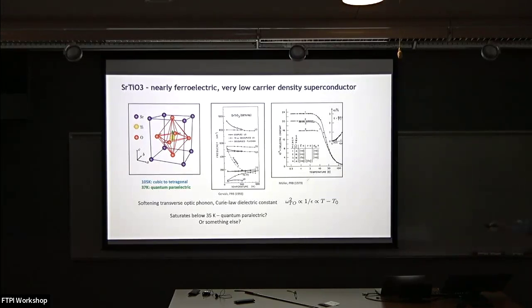You know that because, of course, if it does go off center, it will generate a dipole moment, and the material will become ferroelectric. And the proximity to ferroelectricity involves looking at the dielectric constant, or rather the inverse of the dielectric constant. And so this is rising. This is basically Curie law. And the Curie law heads for what you would have thought to be a phase transition of about 30 Kelvin or so. But then when it gets in the vicinity of that, it saturates.